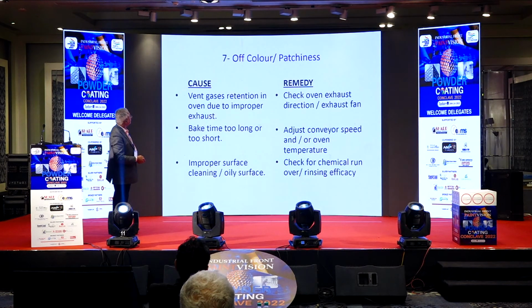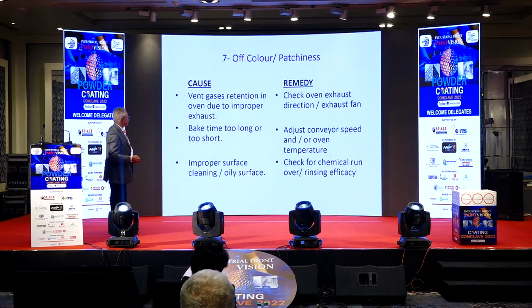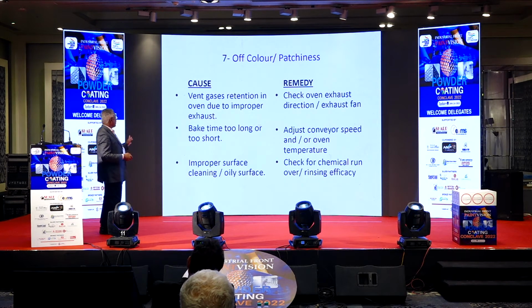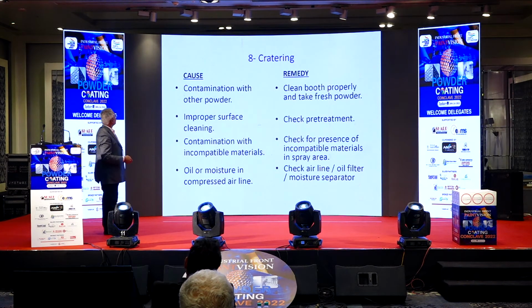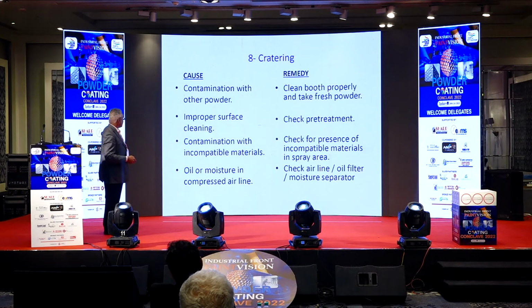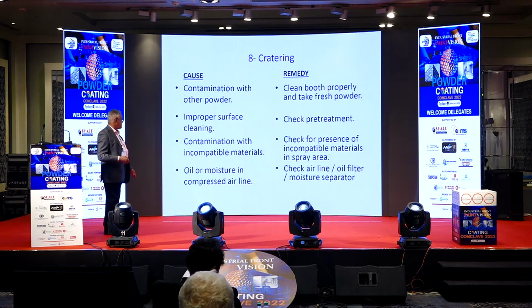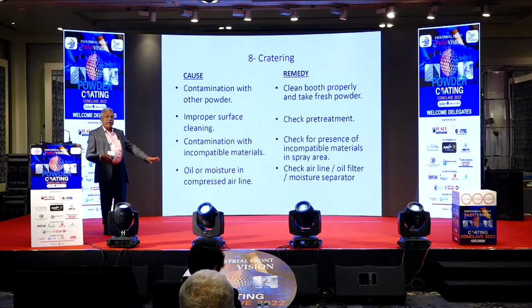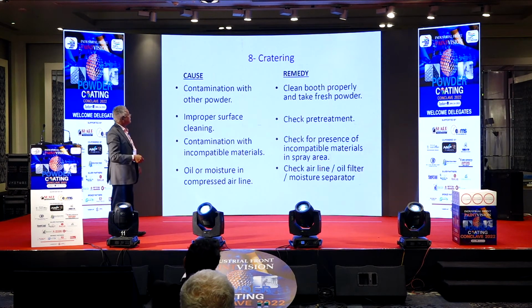These are panel defects. Off color: with vent gas retention, you will get an off color patch. Baking time too long or too short. Improper surface cleaning also causes craters. Craters: contamination with other powder, improper surface cleaning, contamination with incompatible material. Oil and moisture in compressor air during application also cause them.